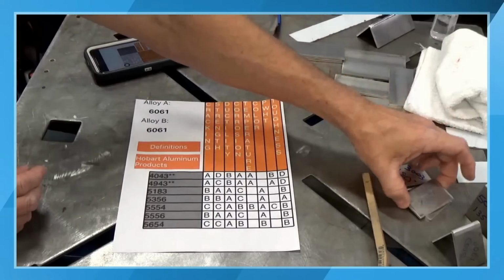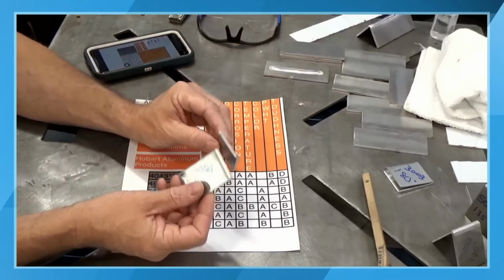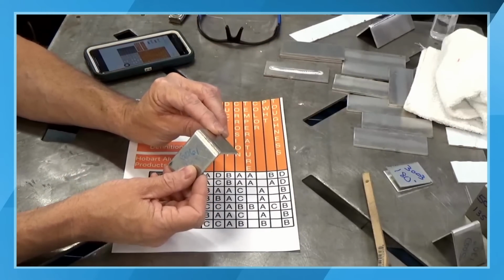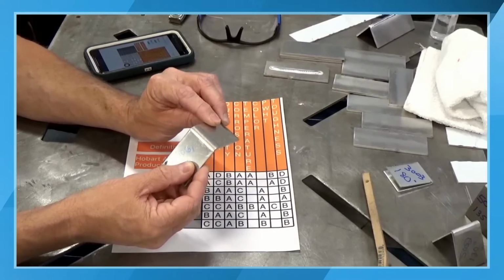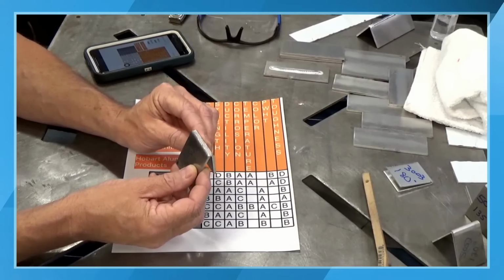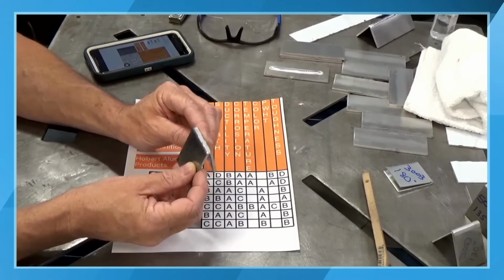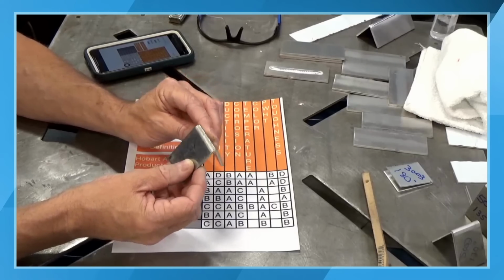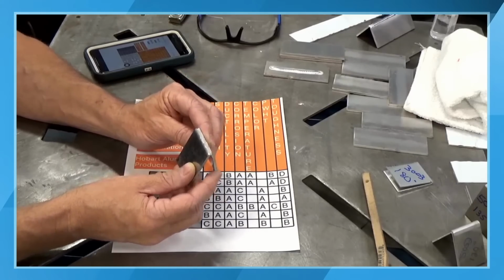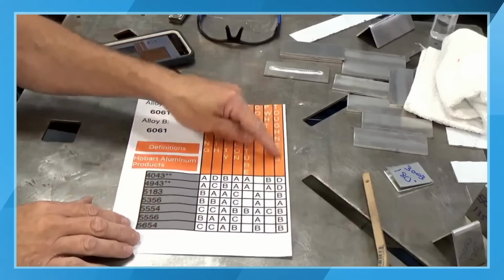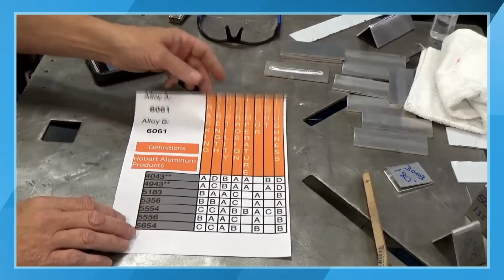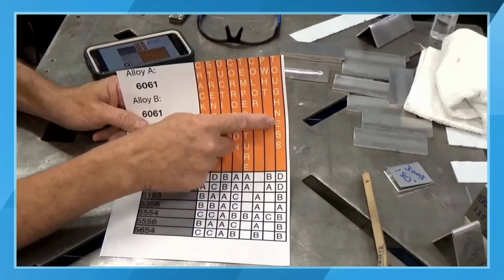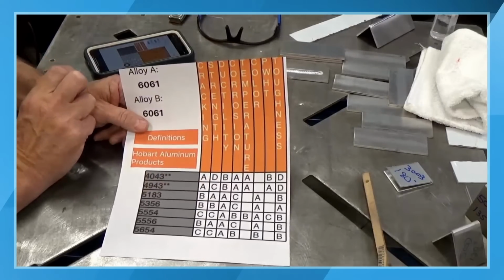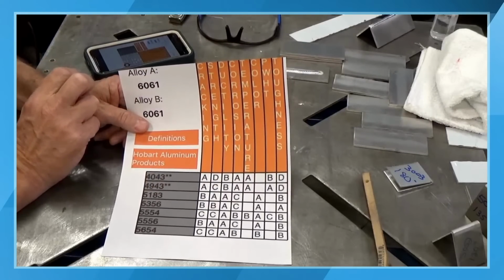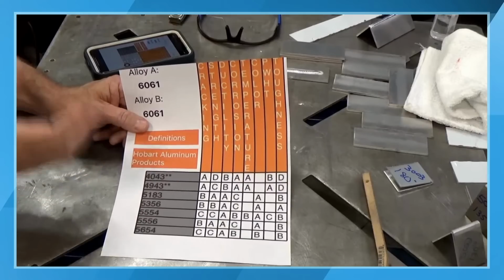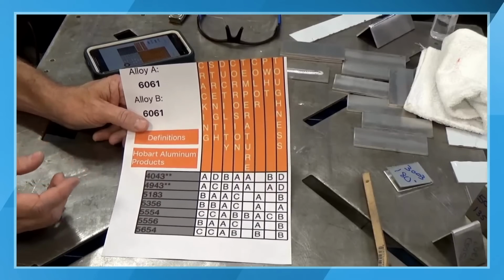So in other words, like this 6061 material, when I bent it, its plasticity was not very good, right? Because it didn't allow me to deform it to the point where the strength was reduced, yet the material still stayed together. That would be the toughness of the weld puddle. So if you're going to be hammering the weld puddle on a planishing hammer, you're stretching it. You don't want to get to the point where it starts cracking.